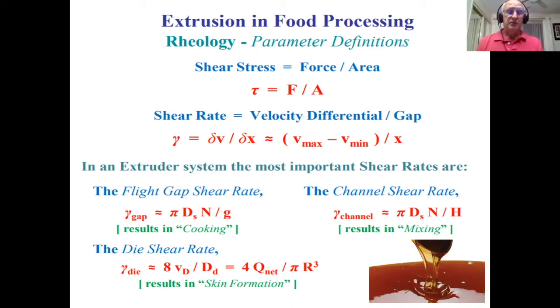So next time you eat an extruded product, take the time to look at the individual product itself, and you'll find the surface characteristics of the product are different to those of the core of the product itself. And this is because the core product has seen all of the channel shear rate and the flight gap shear rate, but only the surface has seen the die shear rate. The core of the product did not. And it makes a significant difference to the visual and functional properties of the material itself.